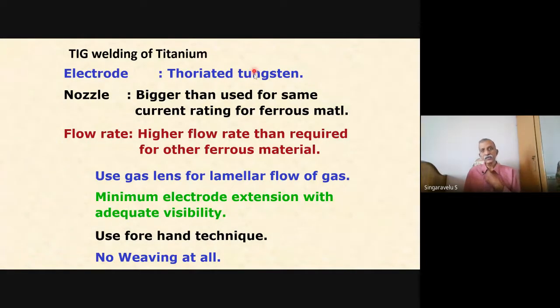The electrode is a thoriated tungsten in the case of TIG welding. Normally, the size will be bigger for the same current rating compared to the ferrous material. Flow rate should always be higher also, right? Use a gas lens for the laminar flow. The flow should be laminar, it should not be turbulent, so that the shielding becomes 100% proper.